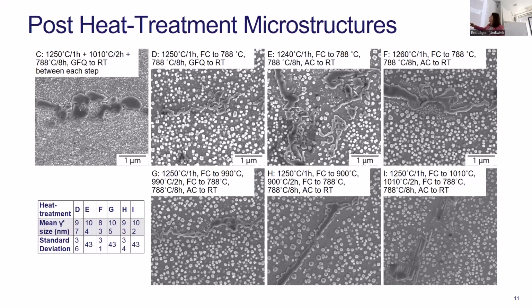So you can see in this one, for example, growing of the gamma prime around the grain boundary, but a distinct lack of tertiary gamma prime coming out. And the reason we wanted to have that was later on when we were testing the creep, to see if that had any effect on the properties.